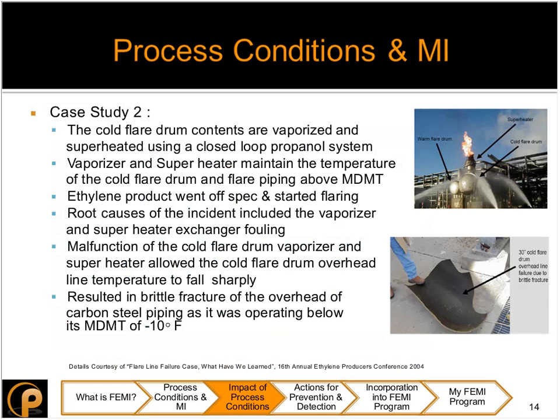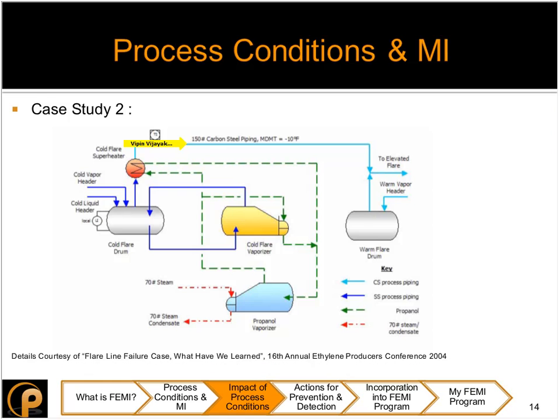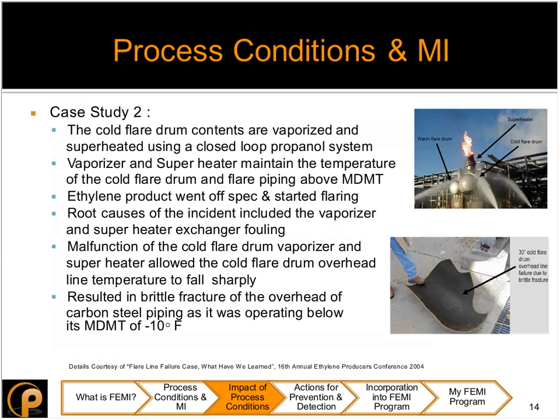What happens is that the cold flare superheater and the cold flare vaporizer have not been maintained properly and have not been operated well over a period of time. It has caused fouling, and it does not meet the heating capacity requirements that are required for the cold flare drum. As a result, the temperature in the overhead line drops below your minimum design metal temperature, and brittle fracture happens on the carbon steel piping because it has gone below the MDMT.